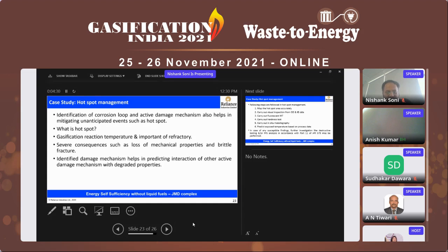Whenever the refractory lining gets damaged, that portion of the reactor experiences very high temperature, which ultimately leads to degradation of the metallurgical and mechanical properties of that particular material. Damage of the internal lining is sensed from outside by measuring the temperature difference between the hot zone and the relatively cold zone, which is identified as a hot spot. In a hot spot, the material temperature is as high as the lower critical temperature of that material, which leads to loss of mechanical properties and increased chances of brittle fracture. This is the reason why hotspots are considered very critical with respect to equipment or piping integrity.